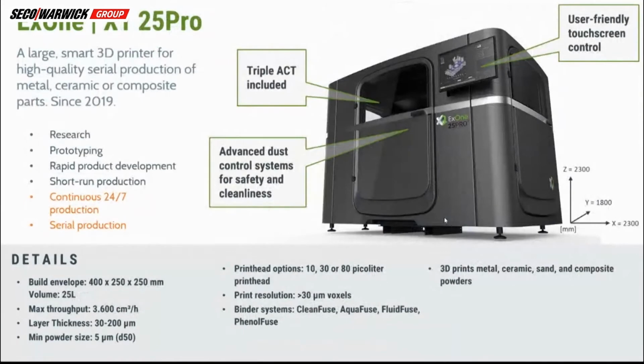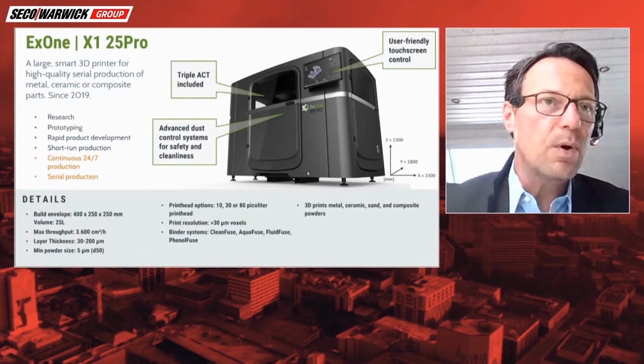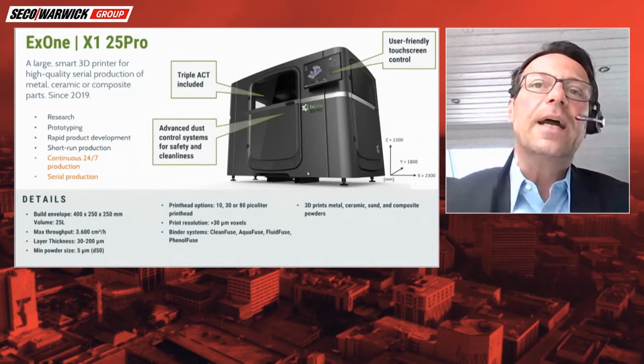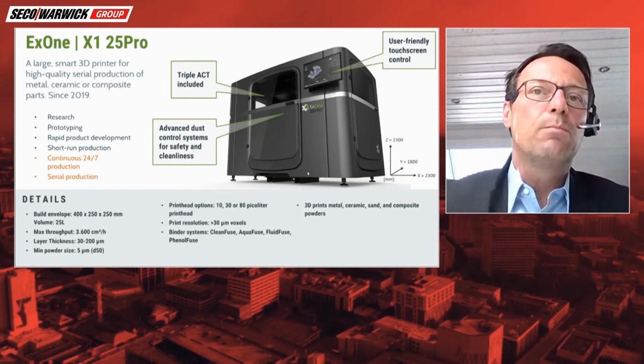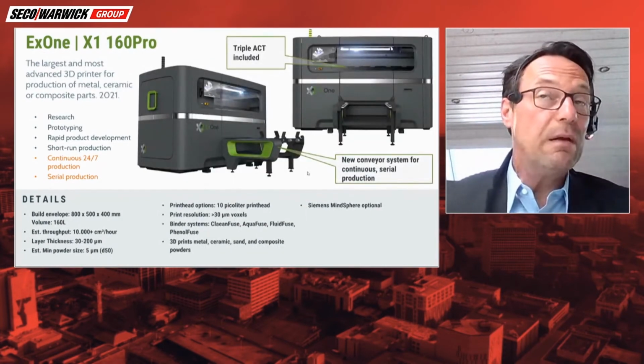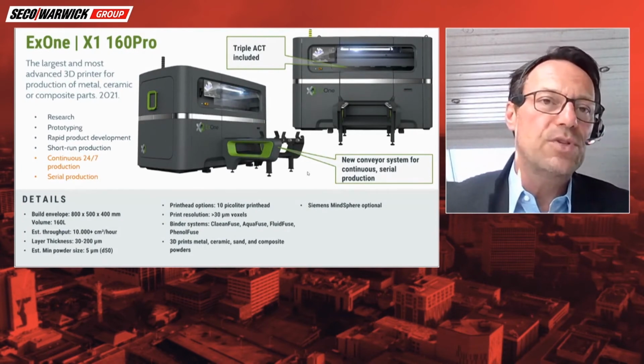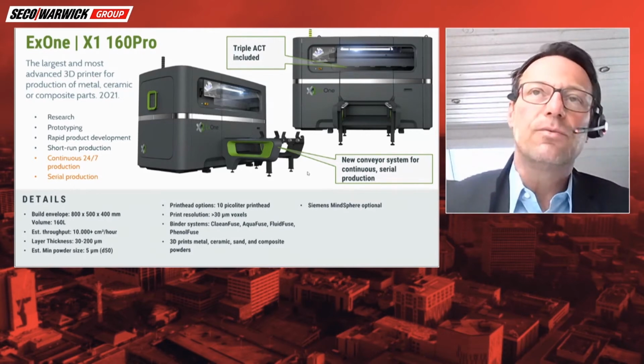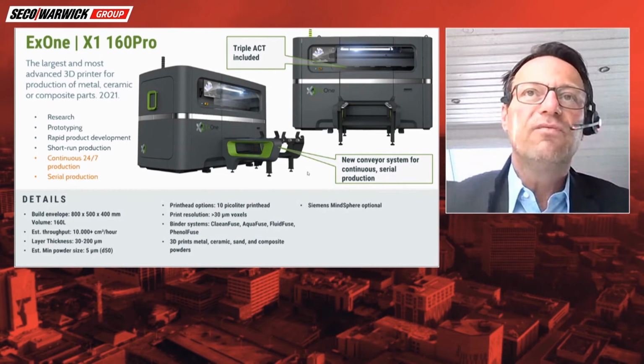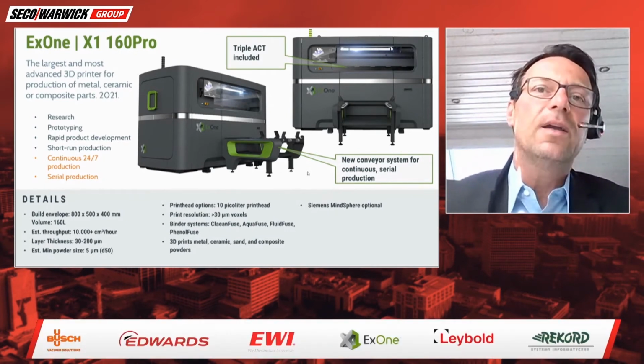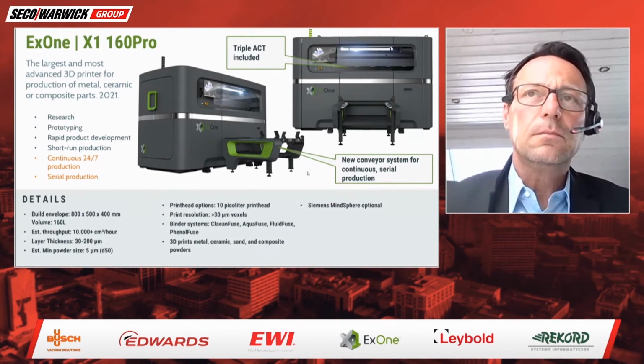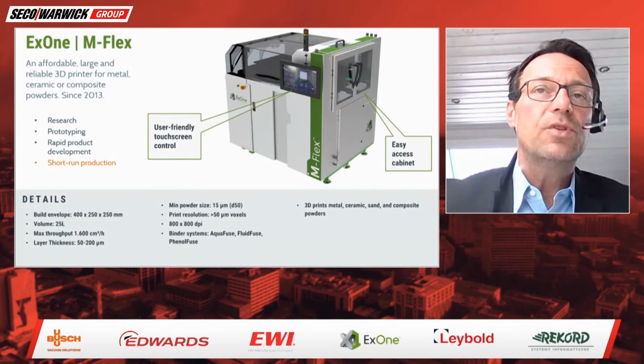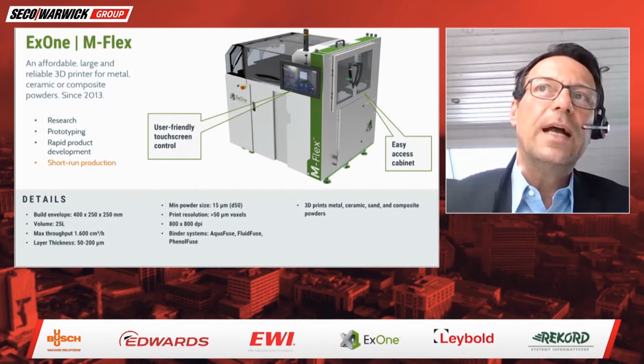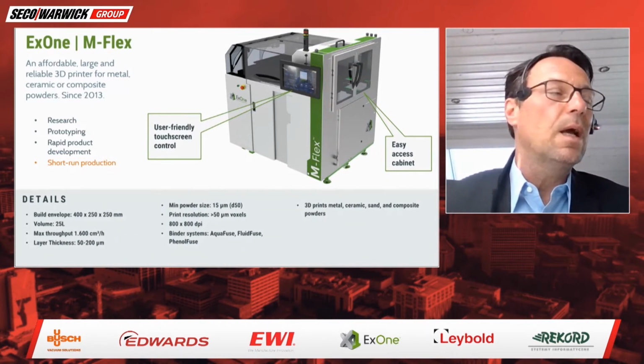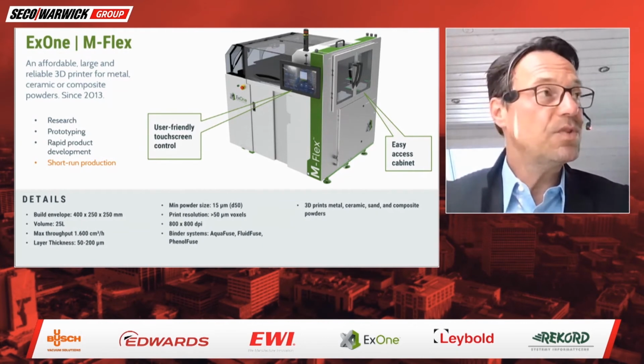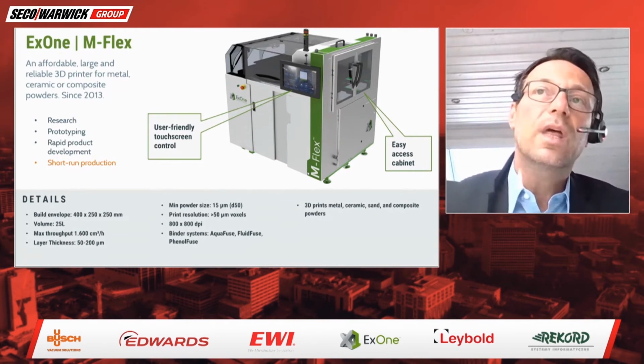The big machine, which we call 25 Pro, the 25 is related to the volume of the build box, which in that case is 25 liters. And let's say this is really for mid-size production of parts. If you want to go one step bigger, we have another machine, which we call 160 Pro. As I said, 160 liters is reflected by the name. So that's the build envelope, the build volume. That's really mass production, high volume production in binder jetting technology. I still want to mention the machine called M-Flex. That is more for people who want to build maybe filters, where you have a more porous, not a high dense material at the end, then you can cope with that challenge using the M-Flex as well.